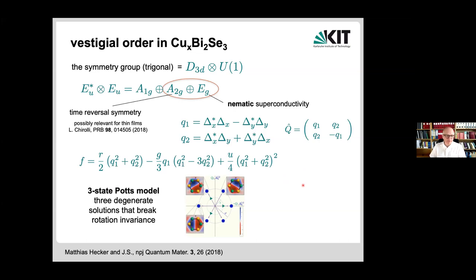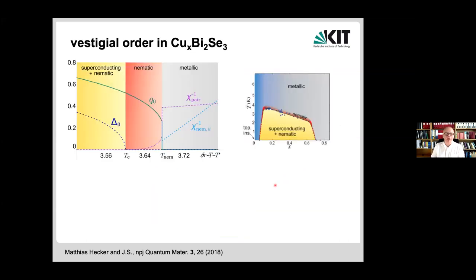We investigated this here with Matthias and analyzed the phase diagram and found that if you take into account fluctuations, you find indeed that above the superconducting transition temperature, where the superconducting order parameter is zero, you do find this nematic Potts order parameter to be finite. There's a first order transition at a finite nematic transition temperature. There's an intermediate nematic phase. That's what the theory says.